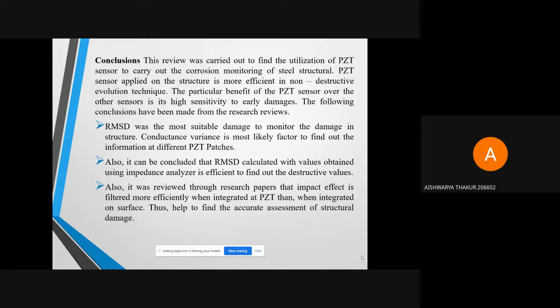It can also be concluded that RMSD calculated with value obtained using impedance analyzer is efficient to find out the destructive value. It was also reviewed through research papers that the impact effect is filtered more efficiently when the PZT is embedded than when integrated on the surface.